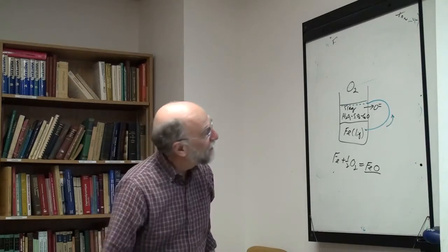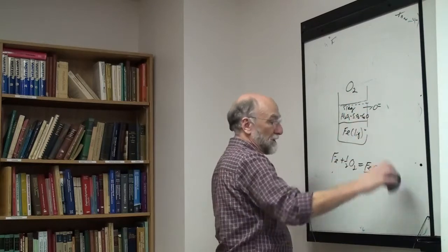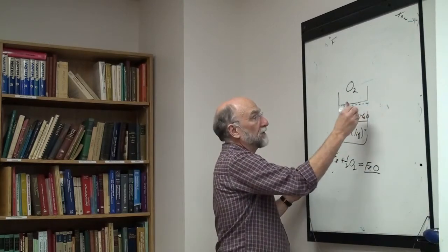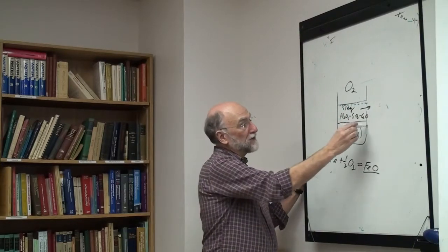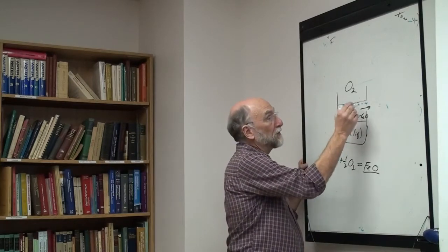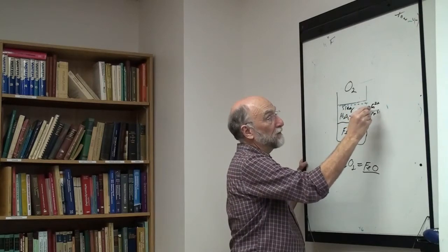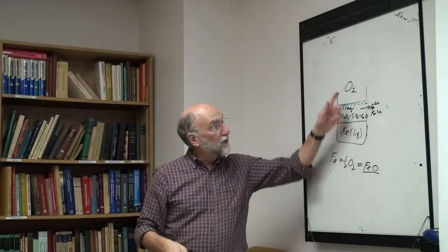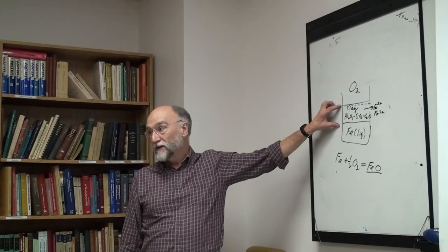Okay. Now, in the slag, however, suppose you replace your external circuit. There's no external circuit, but what we do is we start off with a little bit of iron in the slag. For the example I just gave you, I said the slag was alumina, calcium, silica, completely ionic. We put a little bit of iron in here to start with, 1 or 2%. Now we have iron 2+ and iron 3+, and the slag becomes a partial electronic conductor. Electrons can move through the slag by hopping from 2+ to 3+. So now you don't need an external circuit because the slag itself is your electronic conductor.